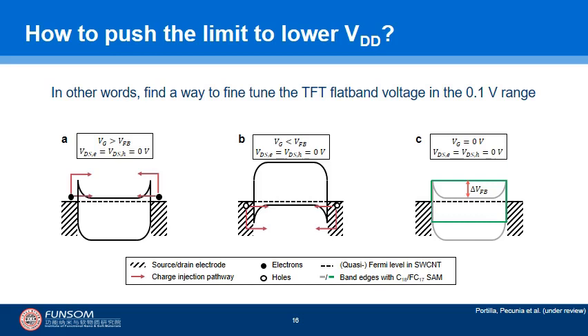In A, the gate voltage is greater than the flatband voltage. Therefore, the injection barrier between source/drain and the semiconductor will be thinned and electrons will be let in. Symmetric considerations hold for the situation depicted in B, which corresponds to hole injection. For the CNT transistors we have considered up to this point, there is an electron current injected for Vg equals 0 volts, which means that we are in the situation depicted in C with the energy bands of the semiconductor corresponding to the ones shown in gray.